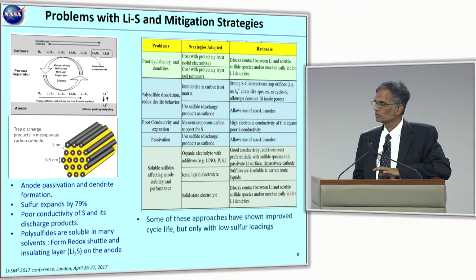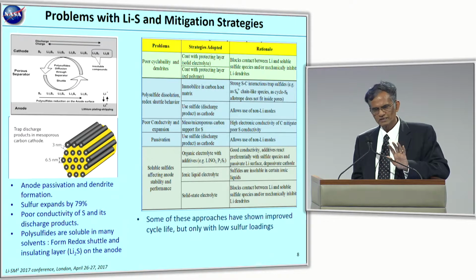The problems are well known with these polysulfide shuttles, and a lot of research has been going on, both in terms of modifying the components at the cathode level, trying to encapsulate sulfur, trying to confine all the products within sulfur, all kinds of membranes, and new electrolytes, be it ionic liquids or combinations thereof. And even protected lithium. People are talking about lithium protected either with a polymeric electrolyte or a solid electrolyte to insulate it from the harmful effects of these polysulfides.